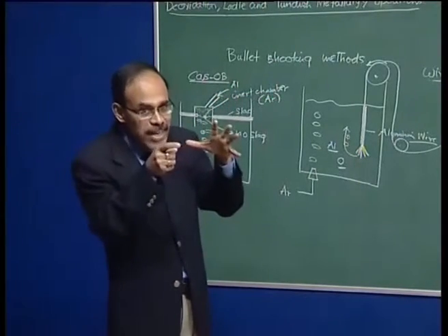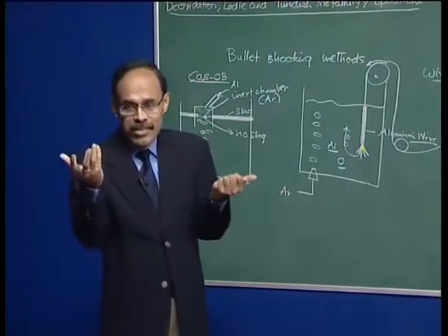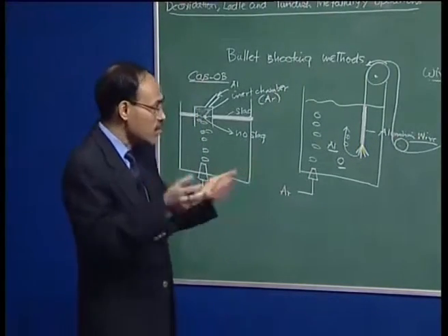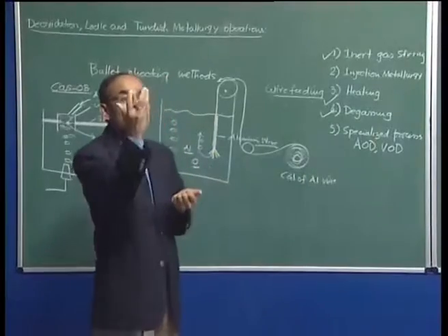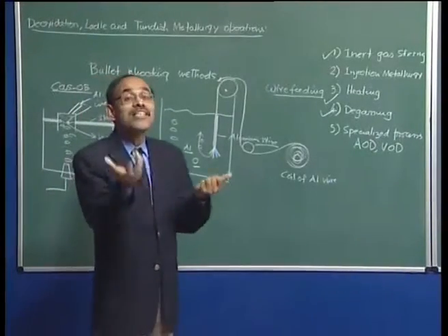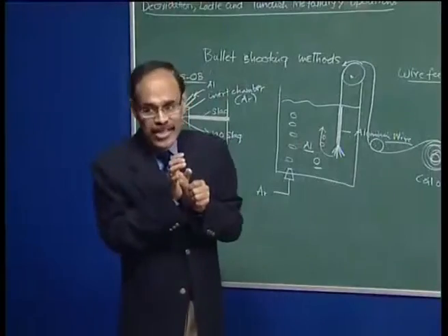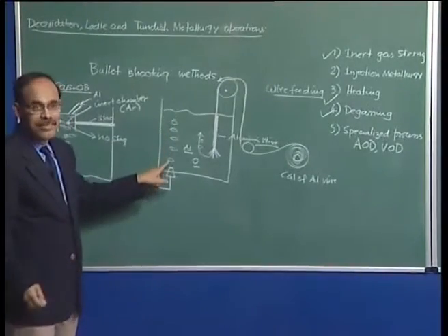So at this particular stage, we really do not want to contaminate. We do not need oxygen. For example, there is nothing to burn there, no silicon oxidation or phosphorus oxidation is necessary. If you introduce nitrogen into the contents of the ladle, steel is going to be rich in nitrogen, that is also not desirable. So basically we are going to introduce argon into the ladle.